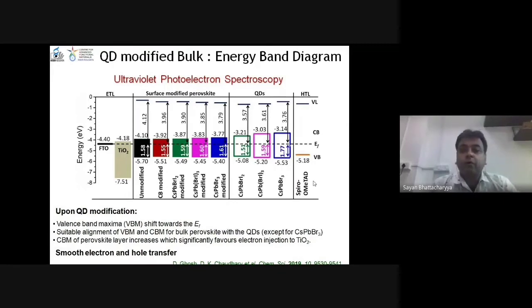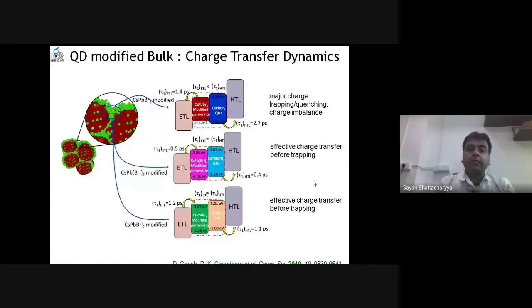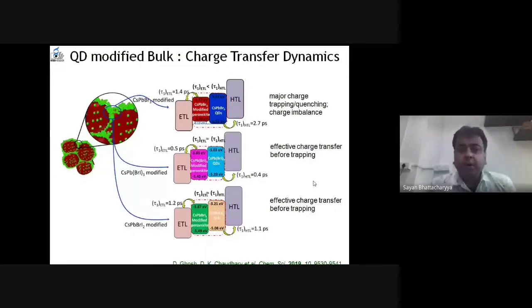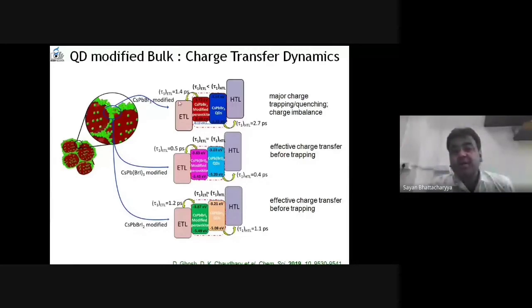So smooth electron and hole transfer is necessary. At the same time, the electron and hole should be transferred at the same time. Now, what is the range of the time scale we are talking about? We are talking about the picosecond time scale. The electron is transported to the electron transporting layer, and the hole is transported to the hole transporting layer. You see that here the time scale is 1.4 picoseconds and here it is 2.7. So they are not similar, and there is a chance of recombination.